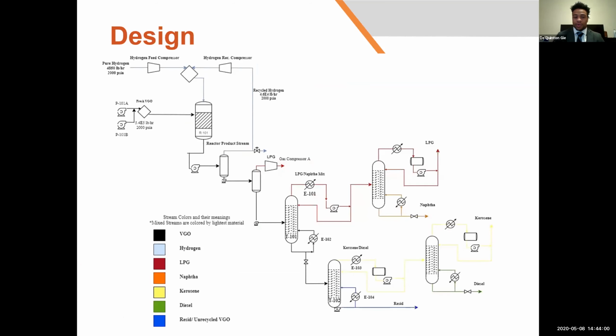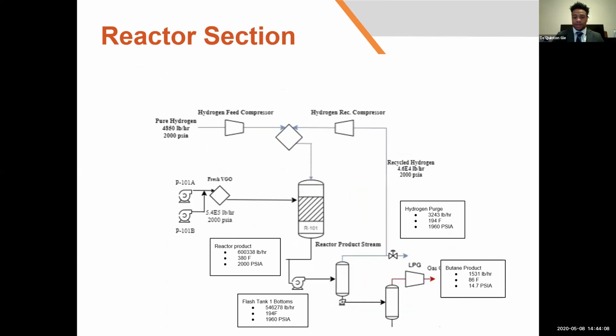As you can see, we have one single reactor, a hydrogen recycle, a high pressure separator, a low pressure separator, as well as 4 distillation columns. If we take a look at the reactor section, our reactor product sends out over 600,000 pounds an hour of a mix of both unreacted VGO as well as the products that we've made. That goes into our first high pressure separator, which helps us recover most of our hydrogen. And then we purge off mostly butane that was unrecovered in that hydrogen stream. And then we send that mix to a low pressure separator, which goes on to our towers.